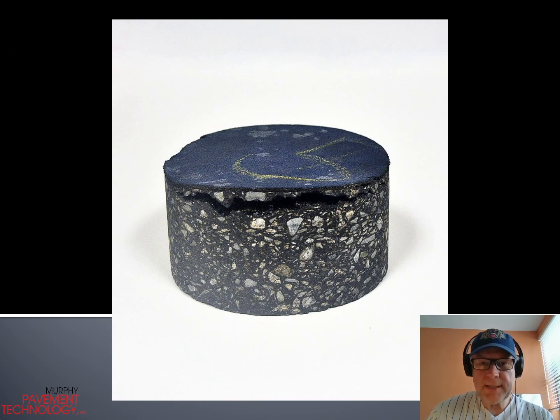This is when moisture gets trapped in the mixture. It actually will fracture the asphalt about an eighth to a quarter inch below the coating, and it's because moisture's trapped. In the summertime, the moisture expands, and the expansion into a steam develops a pounds per square inch that is stronger than the asphalt binder, and it will no longer hold together, and then it rips apart. Many people think it's the coatings causing the problems. The reality in most cases, it's moisture in the asphalt.